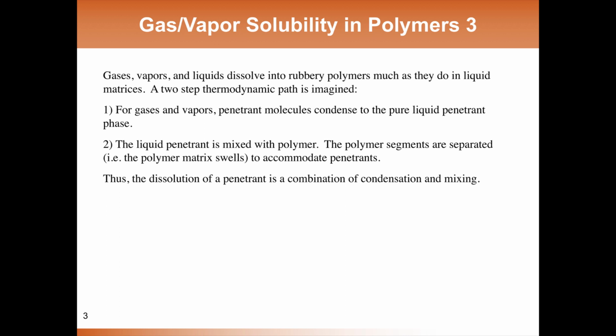We imagine the dissolution of a gas in a polymer to follow a two-step hypothetical path: the gas molecules will be essentially condensed from the gas phase to a liquid-like density, and then the liquid-like penetrant mixes with the polymer segments to form the gas polymer mixture.